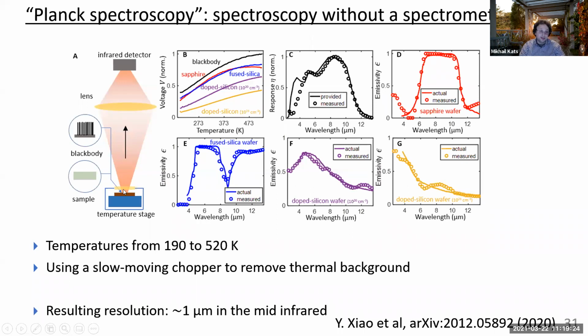So the first thing we did is we put the black body reference here, and we wanted to calibrate our setup. So essentially, we started out saying, we don't necessarily know, for example, the responsivity of our detector versus wavelength. And so we need to know that to be able to do this kind of measurement. So this is what this plot is over here. Essentially, we're using this Planck spectroscopy technique, this inverse problem, to figure out what is the responsivity of the detector multiplied by the transmission of the lens, for example, and the window over here.